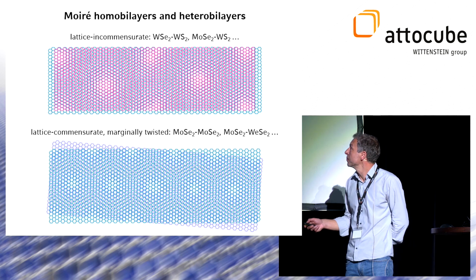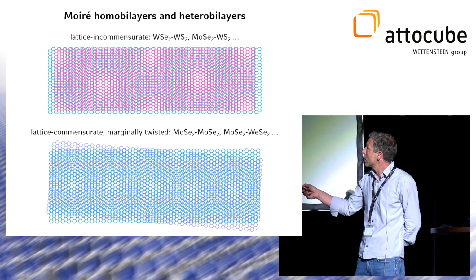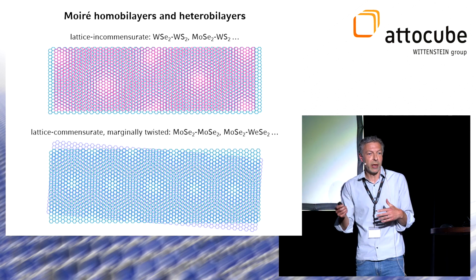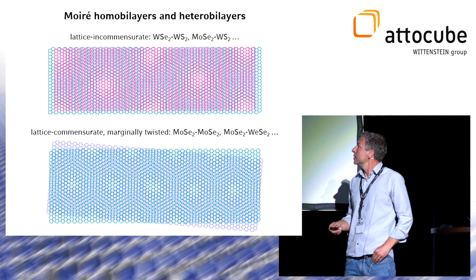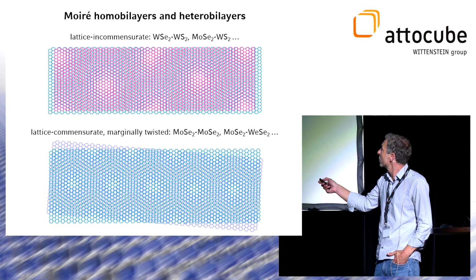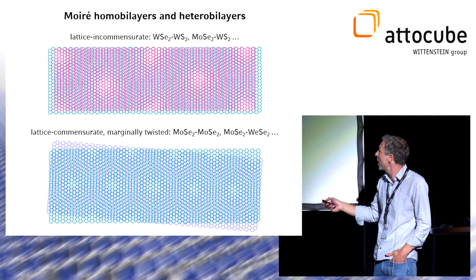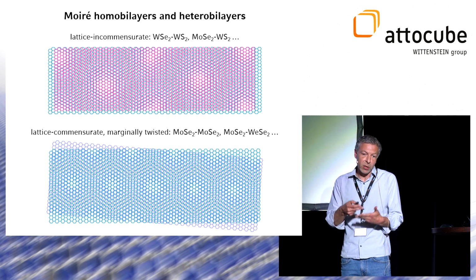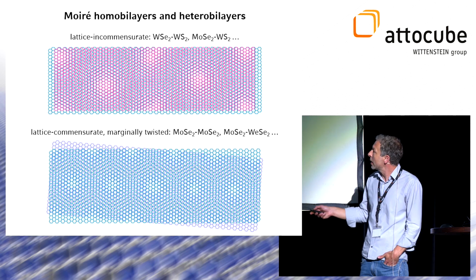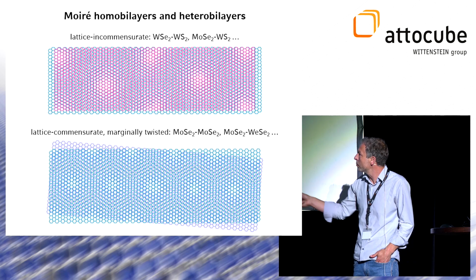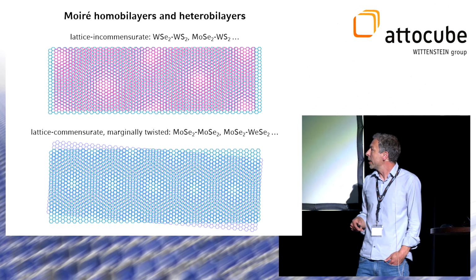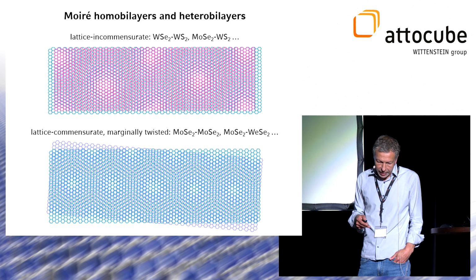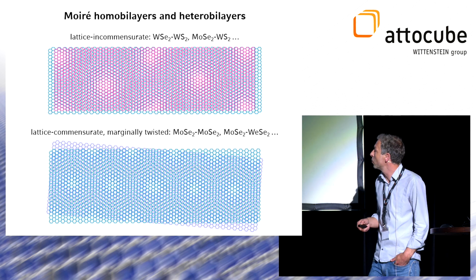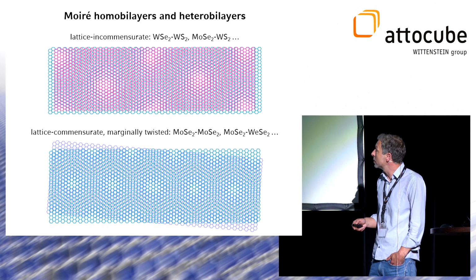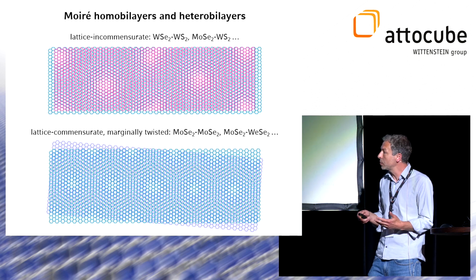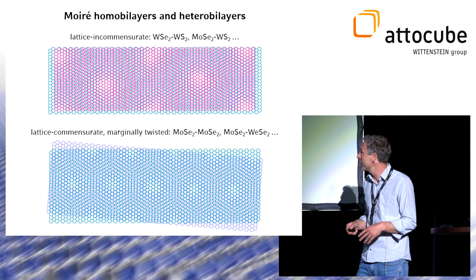The lattice commensurate, marginally twisted homo or heterobilayer, so it can be tungsten diselenide homobilayer, but it can be also a molybdenum diselenide tungsten diselenide heterobilayer. They have very similar or identical lattice constants and at very small twist angles, so if they are marginally twisted, I would like to argue that it's a true challenge to build a true moiré interference pattern that is periodic in space with short and long range order.